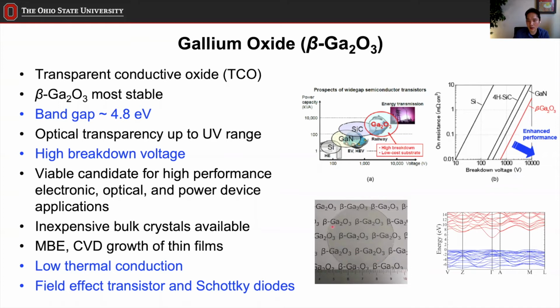So if you have a piece of gallium oxide, it's pretty transparent, as you can see. So it actually gives quite viable potential for being used for optical and photonic applications as well. Among maybe 3 or 4 different phases, beta phase is the most stable one. And as I said earlier, the band gap of this beta phase is about 4.8 eV. And again, it's transparent. And most importantly, gallium oxide has this high breakdown voltage, which is very important.